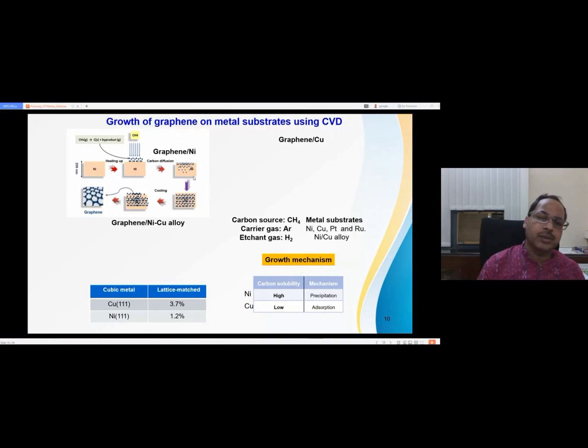Then by controlling the cooling, you can get either single layer graphene or multi-layer graphene. If you do a fast cooling process, you can avoid the effective surface precipitation and get single layer graphene. But if you cool slowly, there is a chance you get multi-layer graphene. So graphene on nickel does not have a very good yield. You can get localized monolayer graphene, but in most places you get multi-layer graphene.